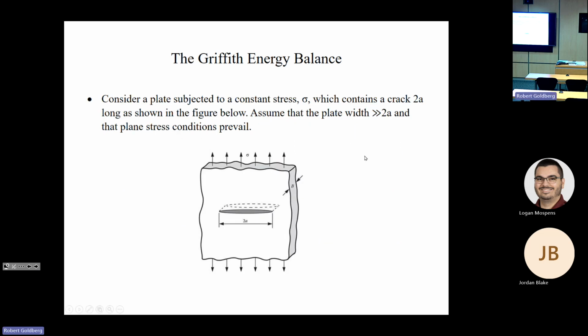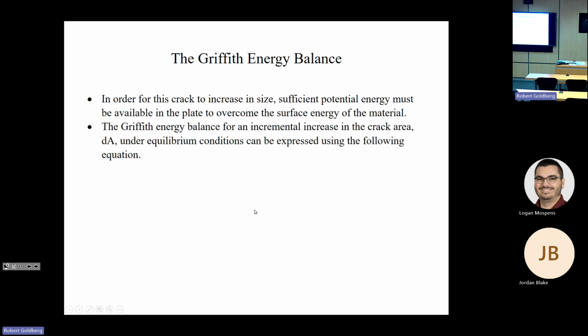So we'll start off, so we'll consider an infinite plate, infinitely long, infinitely wide with a finite thickness B, and we'll assume that this plate is subjected to a constant stress, sigma, and we'll assume that this plate has a crack of length 2a, as shown in this figure here. And we'll assume that the width of the plate is much greater than 2a, and we're also going to assume that plane stress conditions prevail, so that there's no stresses out of the plane of the paper.